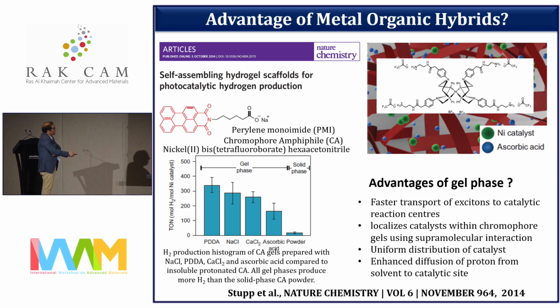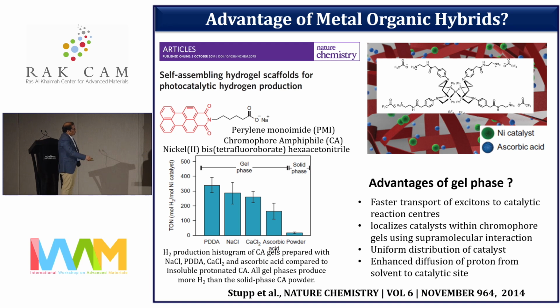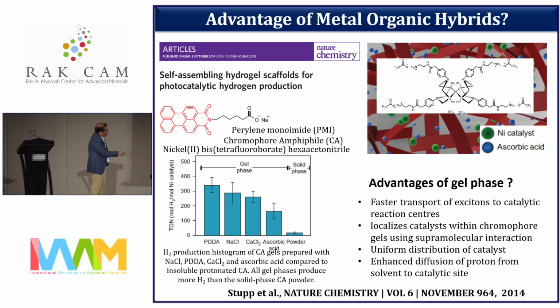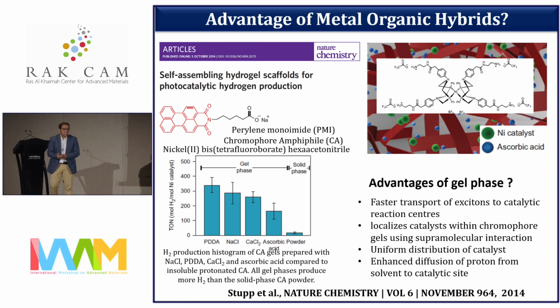What catalytic site did they use? They used nickel, co-localized into the gel matrix non-covalently. When they performed the water splitting reaction for hydrogen production, they found that in the powder state the efficiency is quite low, the turnover number very low. But in the gel phase, this hydrogel, the turnover number is significantly enhanced. This suggests that with these particular nanostructures, exciton separation or migration is faster, localizing the catalyst with the chromophore more efficiently, and proton diffusion from the solvent is much faster since you're using the same solvent system.